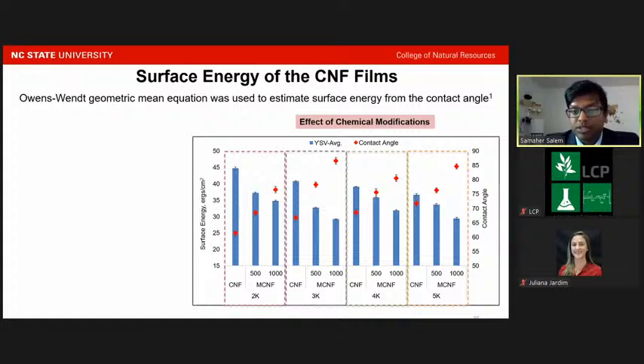This was observed for all the nanocellulose produced at 2, 3, 4 and 5 kilowatt hour per ton energy. And so both the fibrillation and the chemical modification decreased the surface energy and increased the contact angle, and thus increased the hydrophobicity of the nanofibrillar cellulose and also the oil and grease resistance.